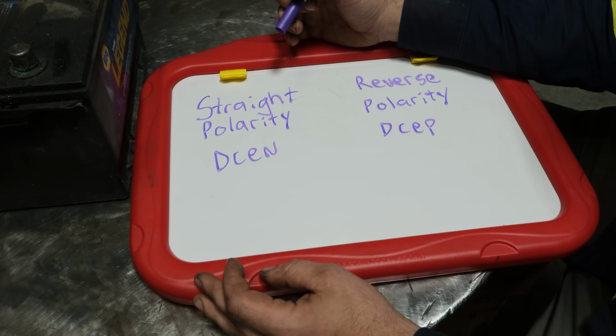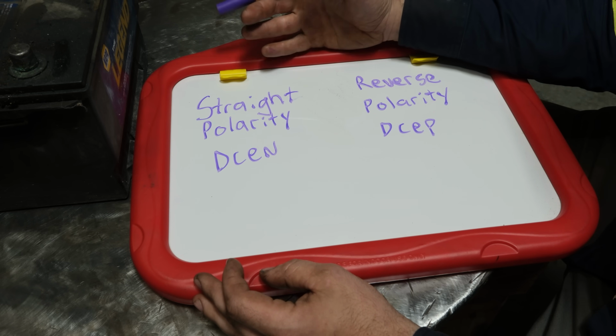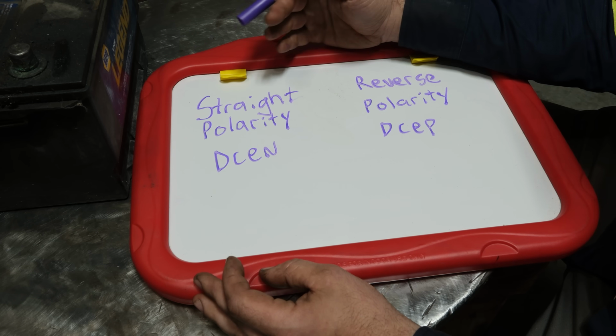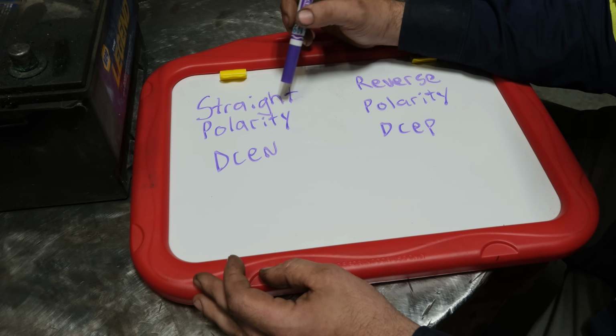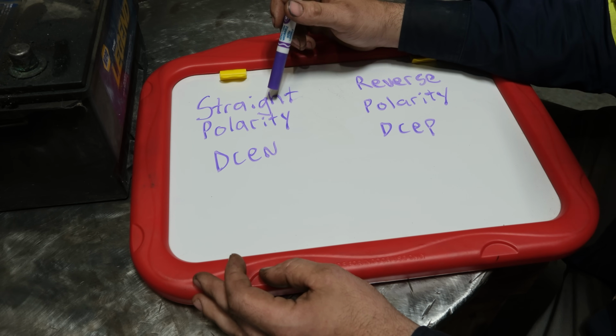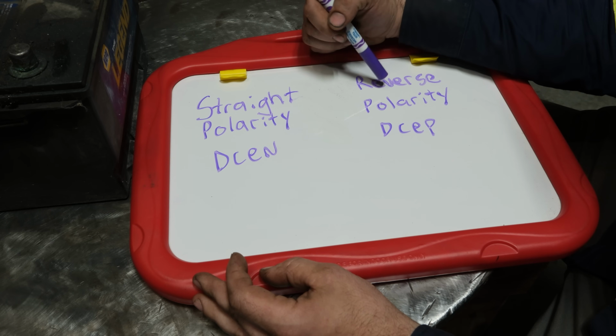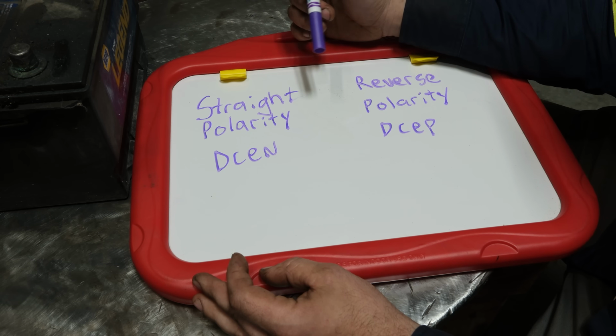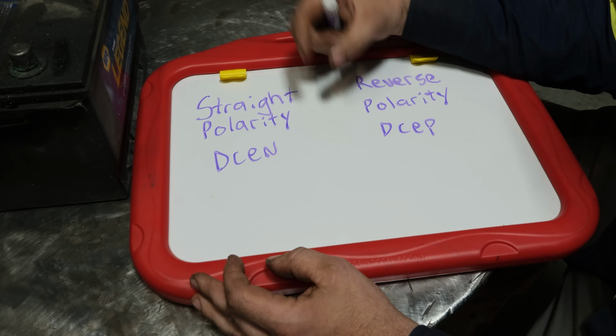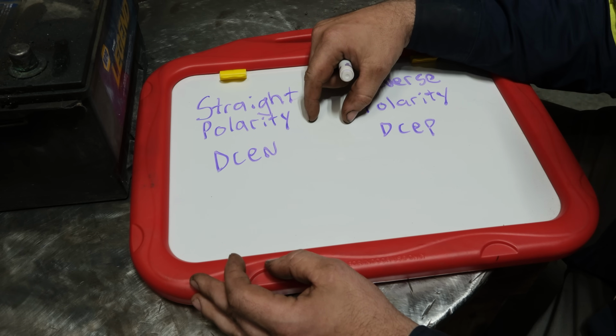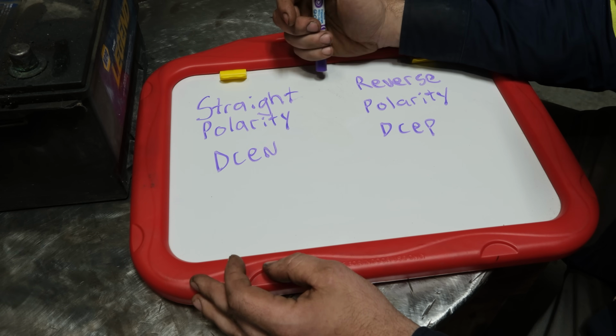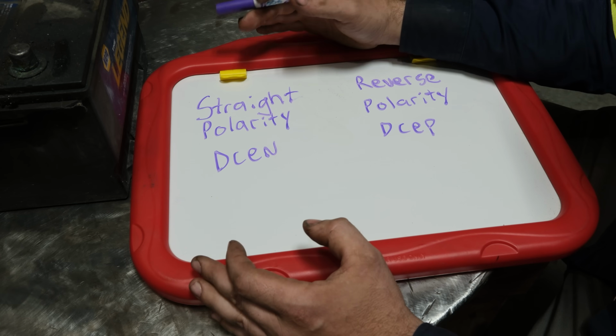And if you have any experience with TIG welding, because in TIG you just have an electric arc and you don't have gas and hot metal spraying everywhere to obscure the arc, this makes total sense. On DCEN straight polarity, the arc is very focused and the tungsten doesn't get very hot. On reverse polarity, the tungsten smokes itself and melts within seconds, and the current or the electrons are coming from the workpiece in a very wide arc cone. So this makes total sense.